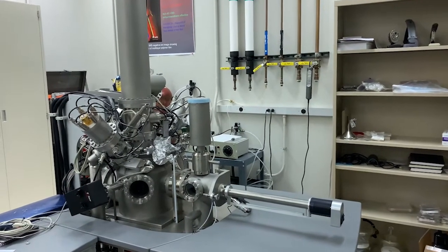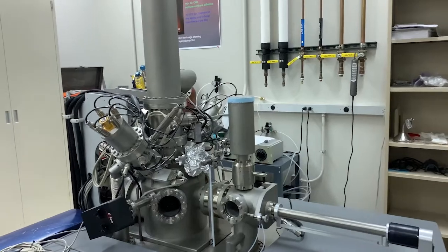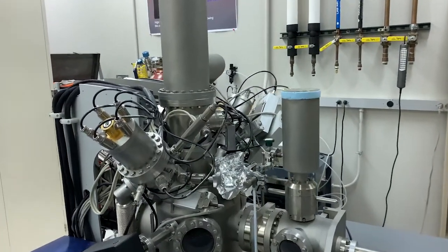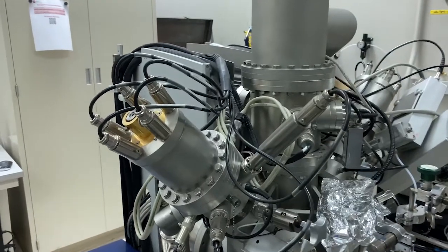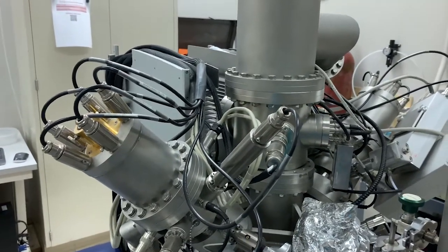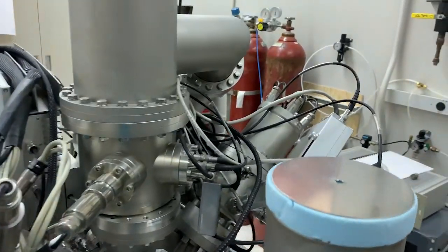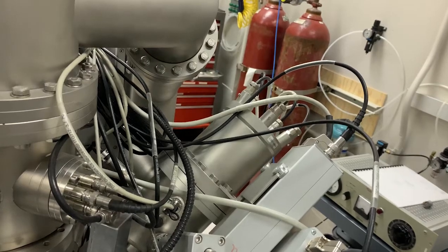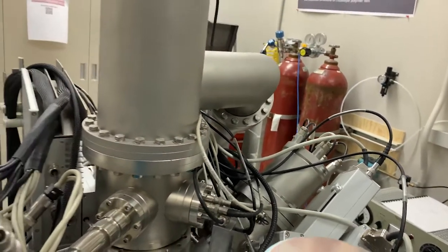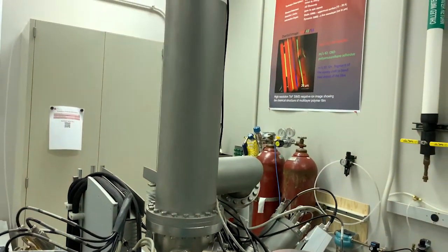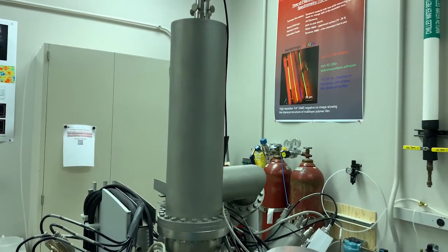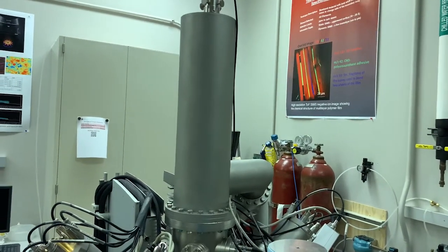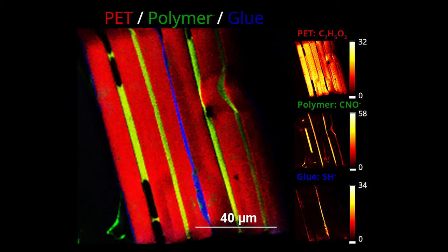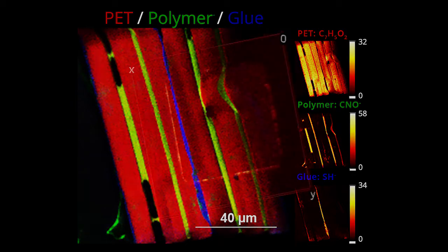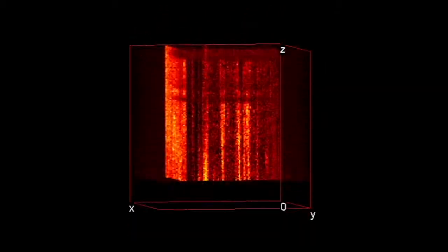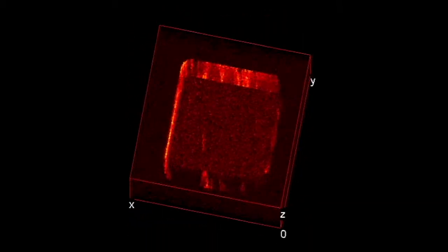So in our ToF-SIMS instrument, there is a pulsed bismuth liquid metal ion source, typically used for analysis beam, and a cesium sputter beam used for depth profile analysis. This vertical tube is the time-of-flight mass analyzer. The mass spectrum collected provides detailed information about the molecular structure of the surfaces. The imaging ToF-SIMS provides a spatial distribution of different species with 300 nanometer lateral resolution, and the depth profile provides elemental distribution from the surface to the bulk with ppm level detection limit and a few nanometer depth resolution.